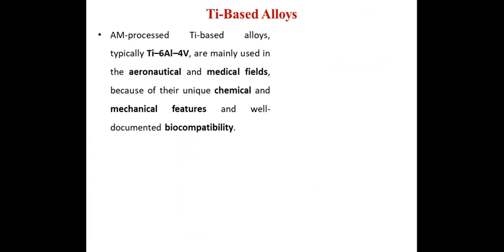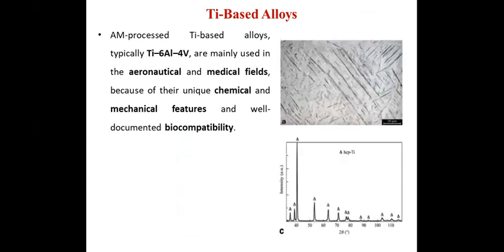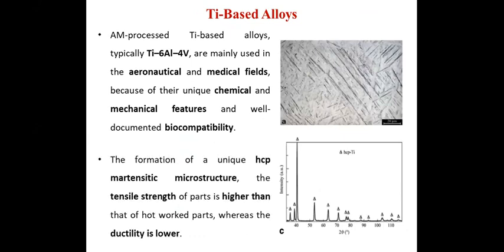When you take titanium-based alloys, Ti64, or titanium 6 aluminum 4 vanadium, is a candidate material for aeronautical applications and medical fields because of its unique chemical and mechanical features and well-documented biocompatibility. With the formation of a unique HCP martensitic microstructure, the tensile strength of the part is higher than that of hot-worked parts, whereas the ductility is lower in this case.